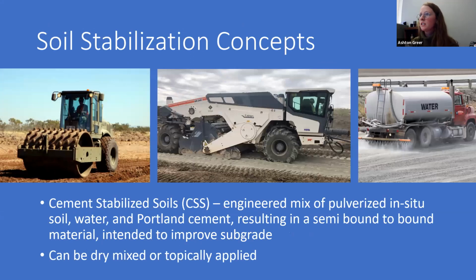There's also context for using cementitious materials to improve our natural soil surfaces. So cement stabilized soils are engineered mixtures of in situ soil, water, and cement, resulting in semi-bound to bound material. They're frequently applied to improve subgrade beneath roadways. They can provide significant improvements to the working platform and permanent soil modifications, and they can reduce the need for thicker pavements and potentially increase pavement lifespans. So in their application, the cement is most often applied in a dry condition, but it can also be applied in a slurry form. And once it's spread, it's generally mixed into the subgrade material and then moistened and compacted. And this often takes place in sort of a convoy, so heavy equipment, one after another, performing these steps in sequence.